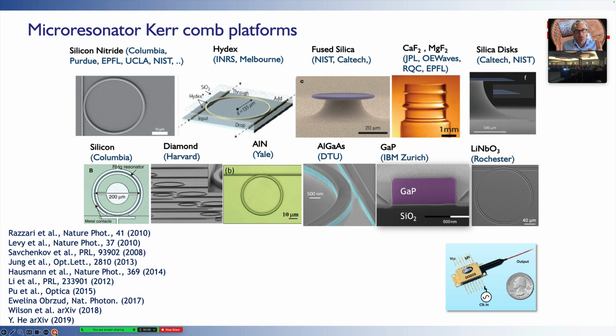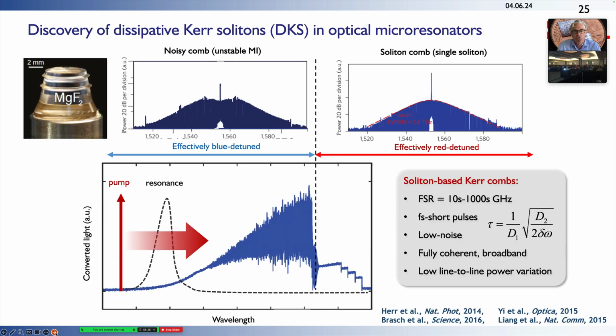Starting with silicon nitride and silica resonators, it has now been observed in almost all integrated photonic platforms. And not only can one generate these optical combs, but one can also produce very short optical pulses called solitons, dissipative Kerr solitons. The way this works is by scanning a laser through a resonance of the microresonator. What happens here is a very complex interplay of nonlinearity, driving and dissipation, by which you first generate a noisy waveform inside the resonator, a so-called chaotic modulation instability state. Then when you tune right through the resonance of the cavity, you enter the bistable regime where you can create so-called dissipative Kerr solitons.